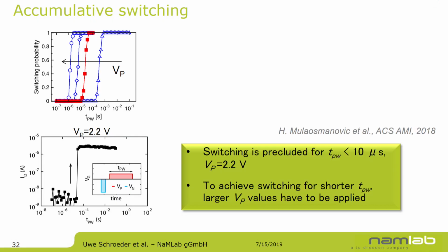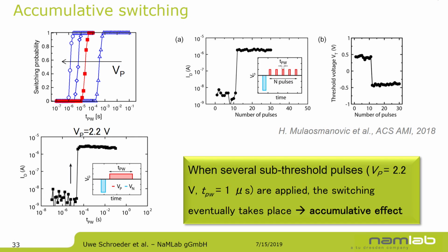So now, you might think this seems very clear. But if you apply one pulse with a certain pulse length to your surface, what's happening if your pulse is below the coercive field? You would expect it wouldn't switch, if your pulse time is short enough. So if one pulse doesn't do it, what's happening if you do multiple pulses at a voltage below the coercive field? In this case, work from Mulaosmanovic, he basically had 10 pulses before he had the switching event, and you switch from one polarization to the other, and the same again for the other direction where you can switch back your device.